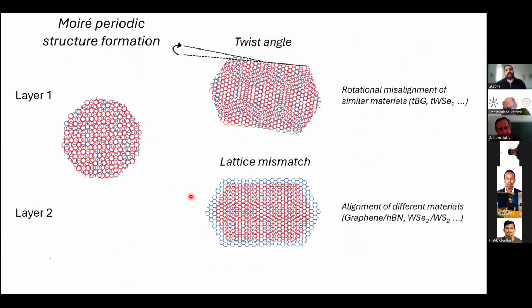And these changes in the real space, in the physical space, will have an impact in the reciprocal space, in the momentum space. And it will change the electronic band structure, and it will affect the optoelectronic properties of these materials, creating, for example, electronic flat bands. In these electronic flat bands, the electron's energy does not vary much with momentum, and therefore the electrons are somewhat trapped, and they can interact with each other strongly, giving rise to all the properties that I mentioned above.